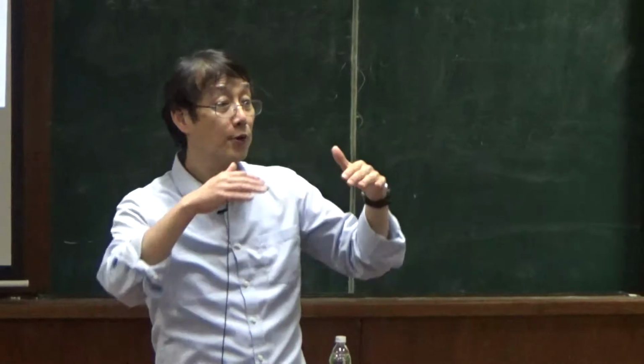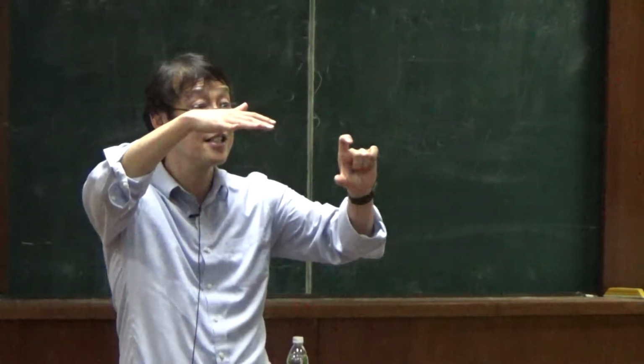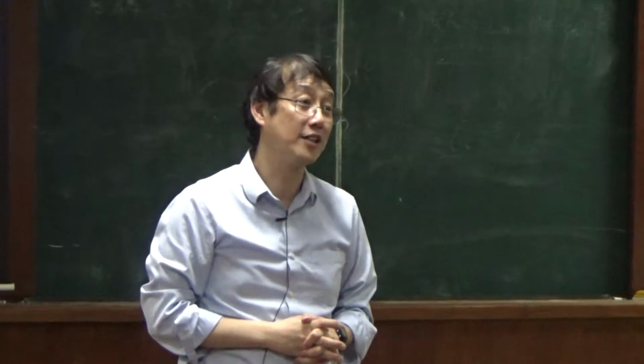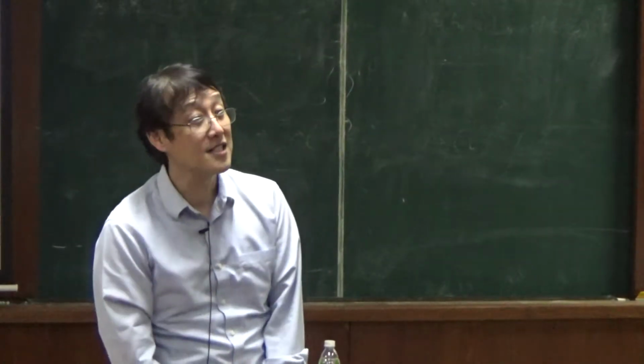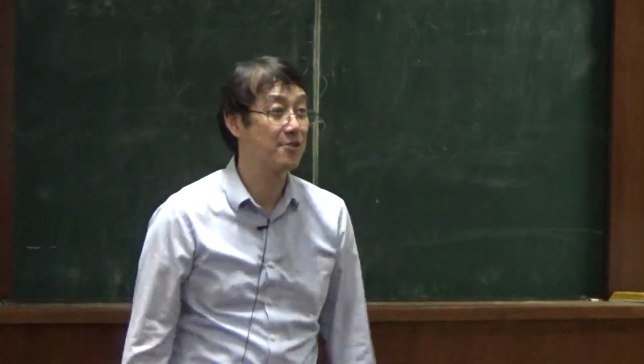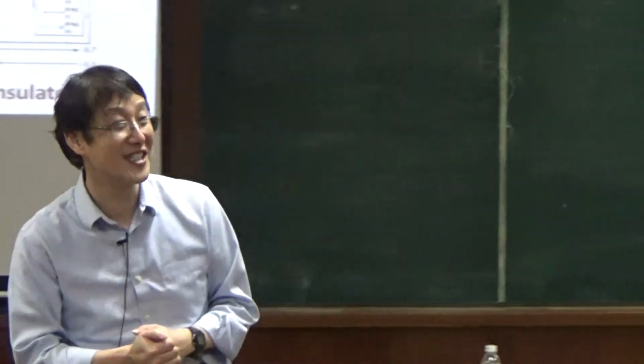And not only the substrate, but also when we put the gate on the top, we need dielectric layers. And there again, the boron nitride serves as a nice thing. So that's why the encapsulation gives such a high quality, right? Actually, the best quality of the graphene sample appears when you suspend the graphene in vacuum, right? But vacuum is very difficult to deal with to make the device. That's why we want to have something close to vacuum, and boron nitride is very close.